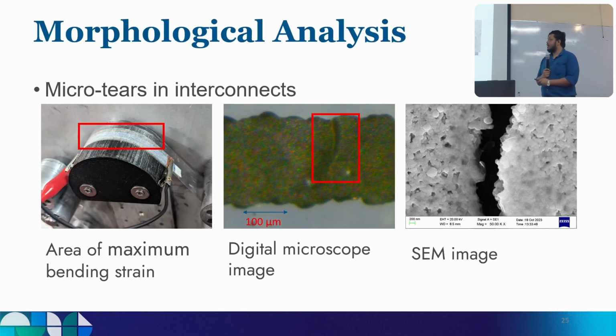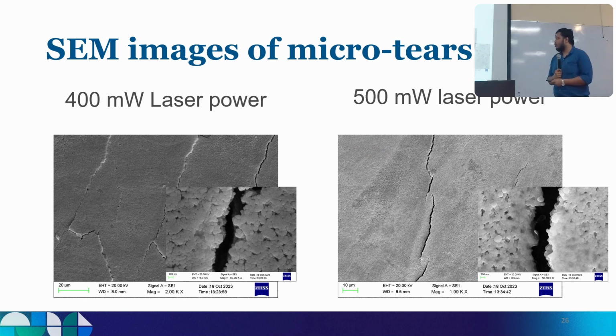This is the morphological analysis, where I took samples from interconnects and then analyzed them under the digital microscopes. If you can see here, there is a very large crack almost to the interconnect, and here is a very small crack which is under 50,000 magnification. These are called micro cracks because they are very small, and these are the ones that keep developing. And so these are some more cracks that are caused by the bending. When these cracks form, we say that fatigue has been reached.